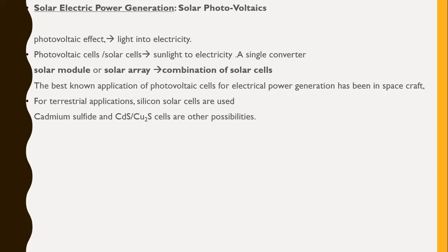So far, efficiencies have ranged from 3 to 8% for these cadmium sulfide cells, and they have been less durable than silicon cells because they degrade with exposure to oxygen, water vapor and sunlight, especially at elevated temperatures.